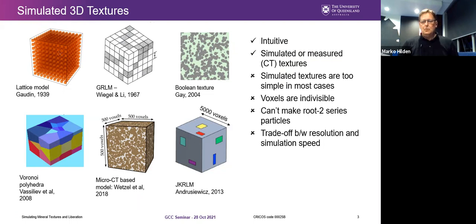A popular method, and one that I've followed as well, is to define a 3D geometry that represents the unbroken ore texture. And Gaudin's model is considered to be the first of this type of model. It's just a simple grid of uniform grain sizes. But this turns out to be way too simplistic in practice. Wiegel improved on this by randomizing the grain positions, though still with a uniform grain size for both phases, but it isn't much better accuracy-wise. But both Gaudin's and Wiegel's GRLM have analytic solutions, so that's a positive.